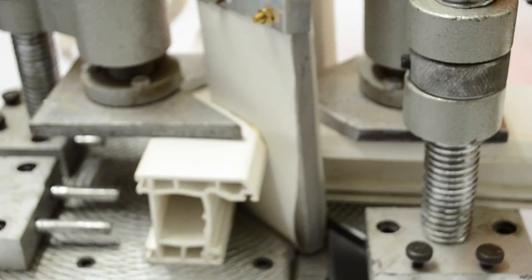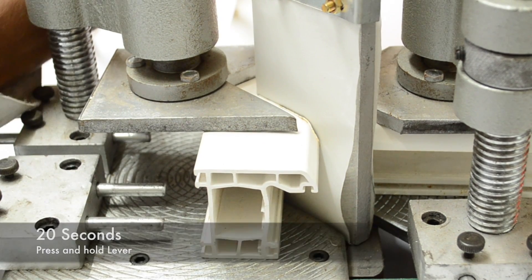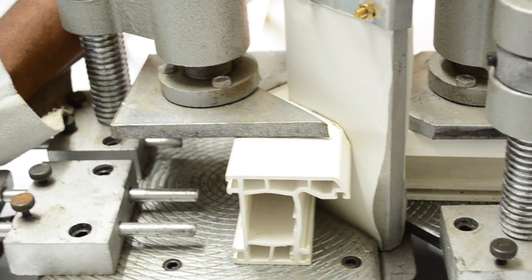When the temperature reaches 150 degrees Celsius, you can use the heat bag. Position the heat bag in between the profiles and press and hold the rear lever for 20 seconds.